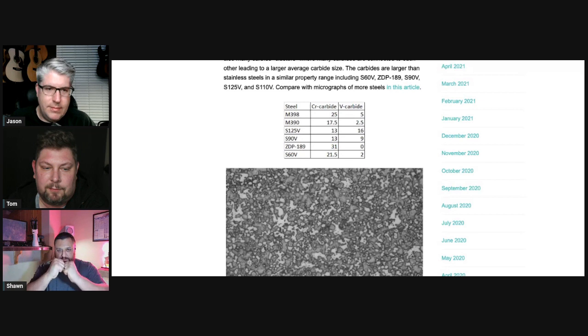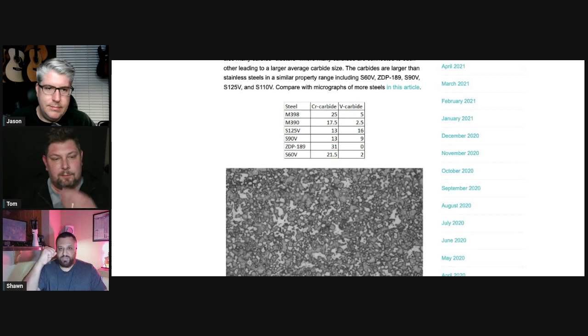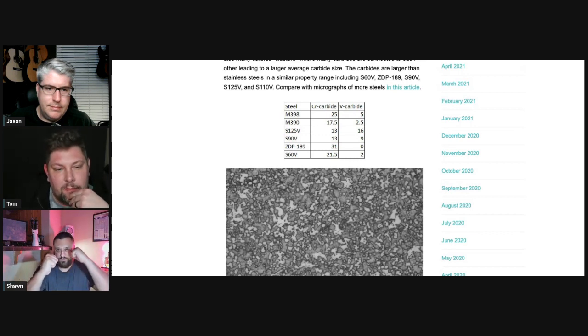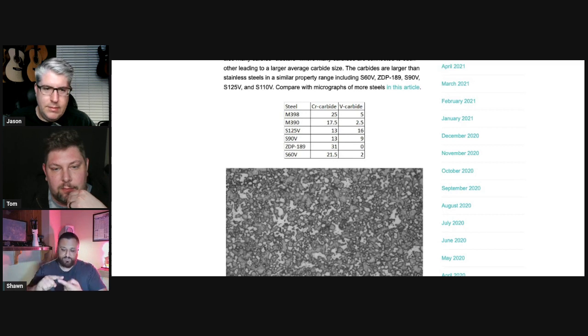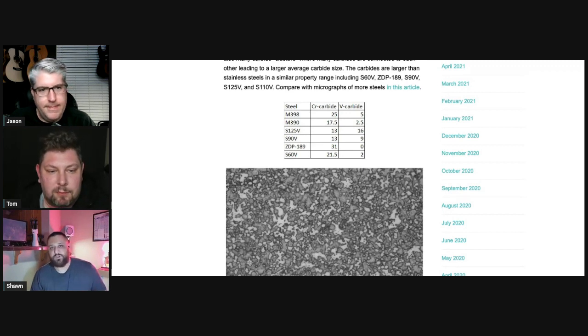So if the metallic element is not in solution with iron and the carbon is not in solution with iron, then basically the metallic elements that are left over or undissolved after heat treatment stay locked together. So you have carbon and the metallic elements that we have in steel, such as tungsten, vanadium, even titanium, things like that, which we don't see in steel because they're too strong of a carbide former. But those will be locked together to make carbides. And those are those little white dots you guys see in these pictures right here.